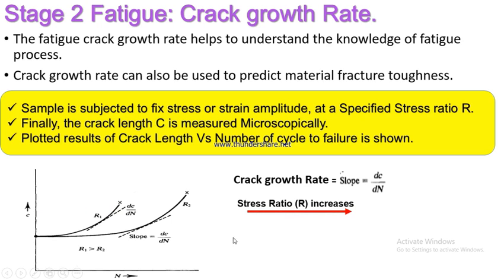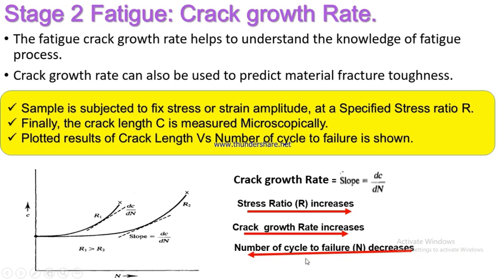Like I explained in the first part of this slide, the meaning of stress ratio: as the stress ratio increases in the material, the crack growth rate also increases. That is what this profile is telling us. The number of stress cycles to failure will decrease. So as the stress ratio increases, the crack growth rate is also increasing, and the number of cycles to failure is decreasing.